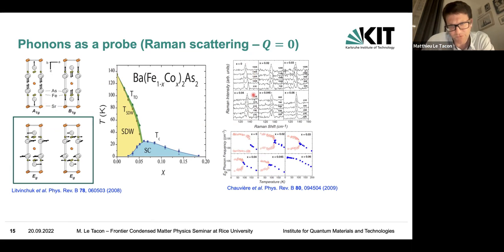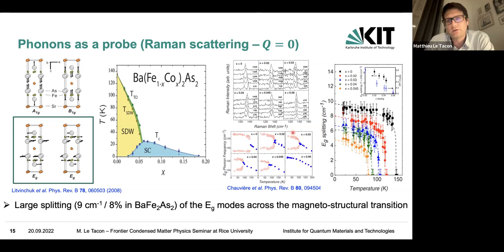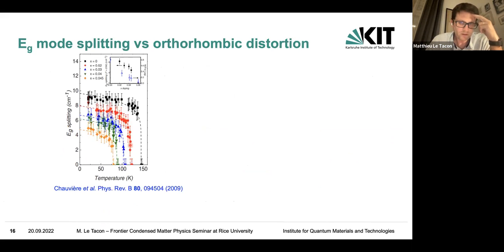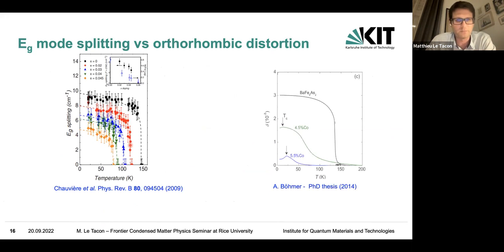Now, the splitting that they observed was quite consequent. I mean, it was actually something like nine wave numbers. So they followed it as a function of doping and temperature. And it was quite a sizable splitting. Actually, they note in that paper that the splitting is in fact much too large to be accounted for by the structural distortion. That being said, I asked the other day, I mean, we did have some data.